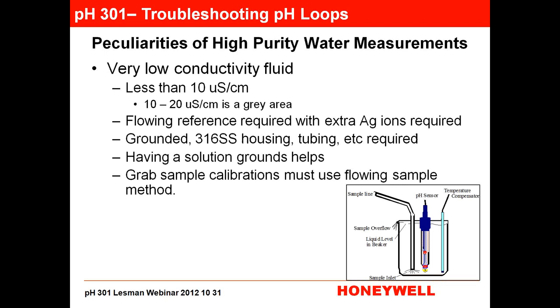Peculiarities of high purity water, I just want to hit this real quick because that's also a problem that I see very commonly out there in some power plants, is that when you take a grab sample of boiler feed water, water that's below 10 microsiemens, it is very, very ultra sensitive to contamination because there aren't very many ions in it. It's super clean. And if you are taking a grab sample and you just pull the sample and then walk over to the counter and put your portable device in there, the likelihood is it's going to be different than what you're reading online. What you're reading online is sealed from the atmosphere.